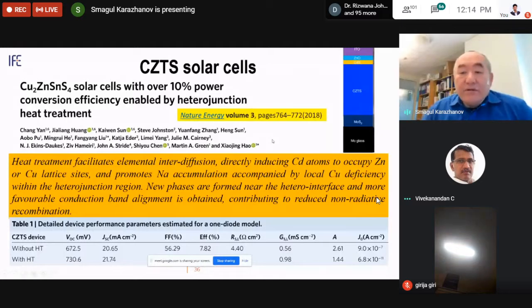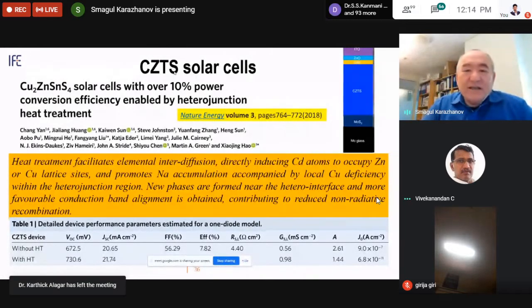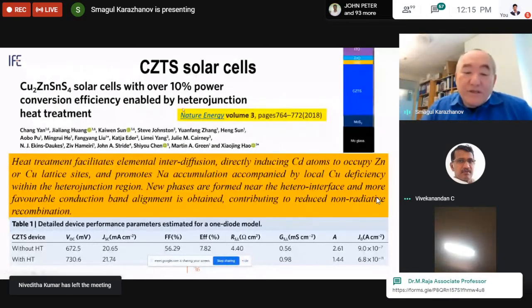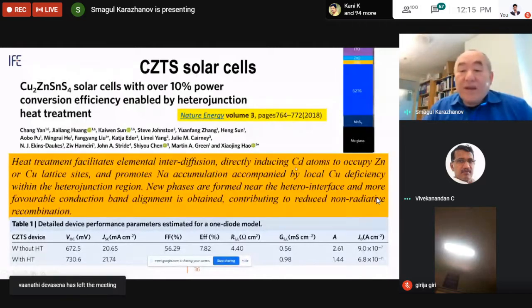So then up to 2018, efficiency of the pure CZTS cells was too low. It was about maybe 6-7%, but then a breakthrough was achieved up to 10% efficiency, which is very promising, and the paper was published in Nature Energy in 2018. The idea was performing heat treatment to provide diffusion of cadmium to occupy zinc and copper sites.